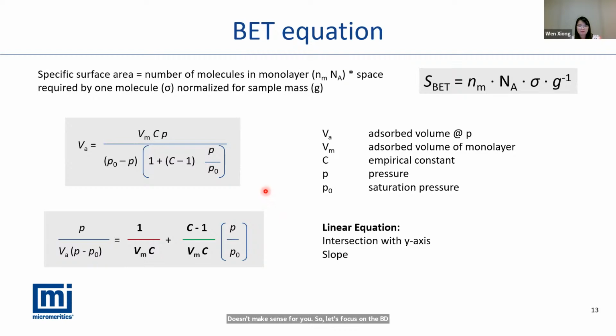We can see from these two equations how the BET model calculates the surface area. If we want to calculate the surface area, we need to use the adsorption data to determine the amount of gas adsorbed on the surface. Then we use the BET equation, which describes the amount adsorbed as a function of pressure here.